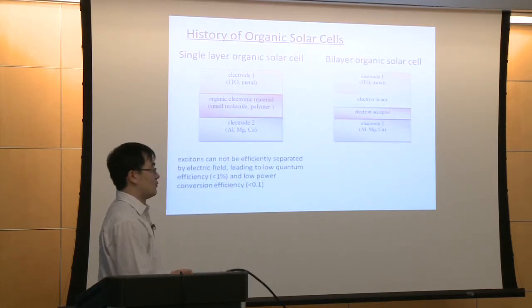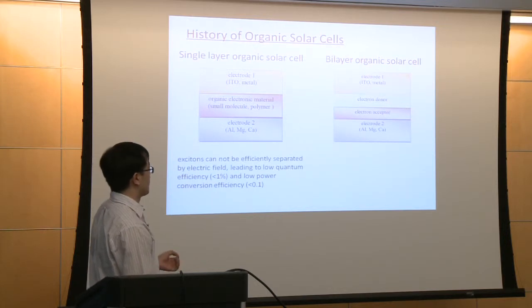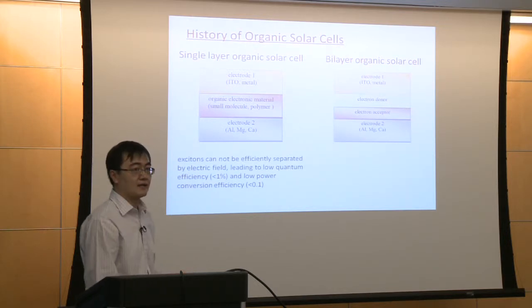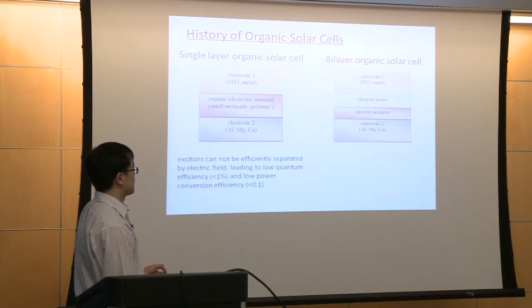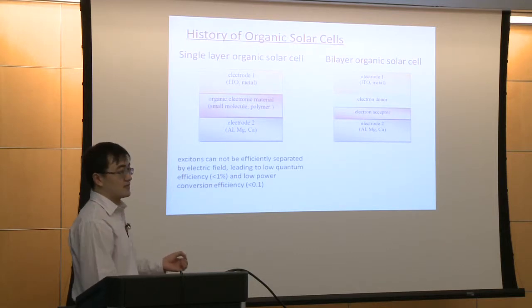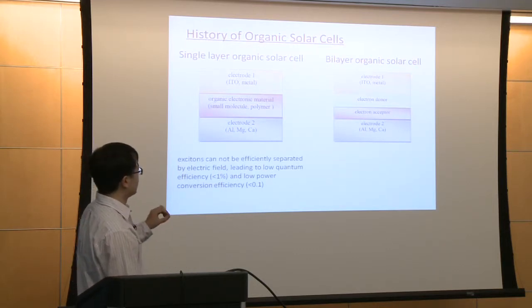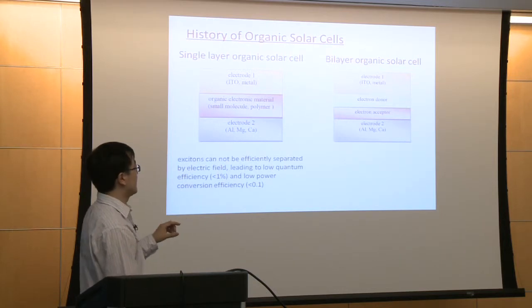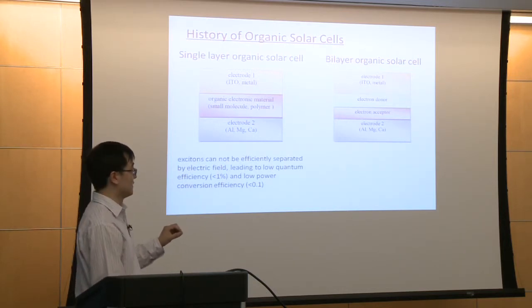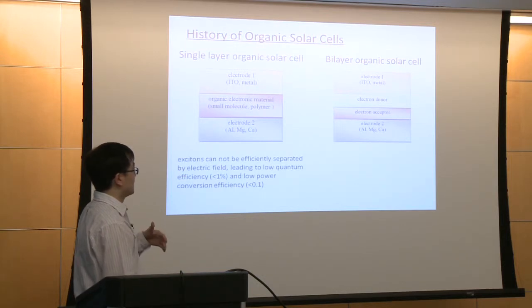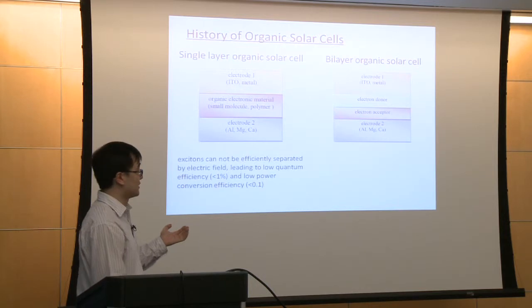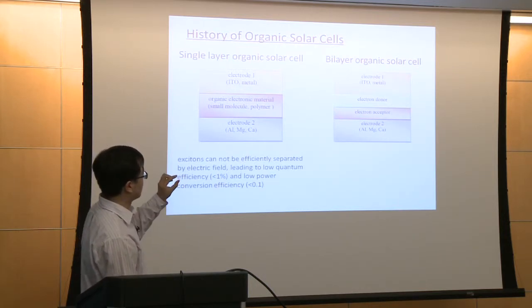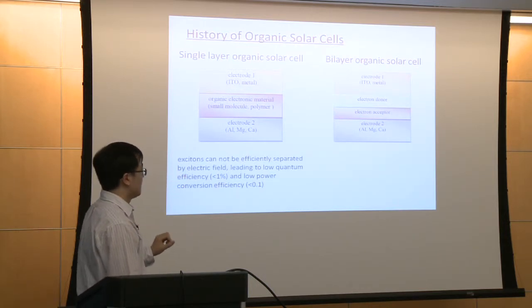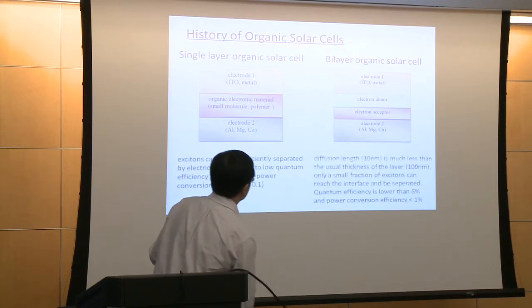So scientists developed another kind of solar cell after several years, which is called the bilayer organic solar cell. In this case, scientists divide the middle layer into two layers. One layer is the electron donor layer, and the other is the electron acceptor layer. So in this case, the excitons can be efficiently separated at the interface between the donor and acceptor layer. However,